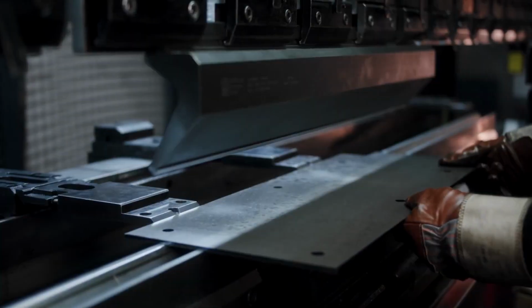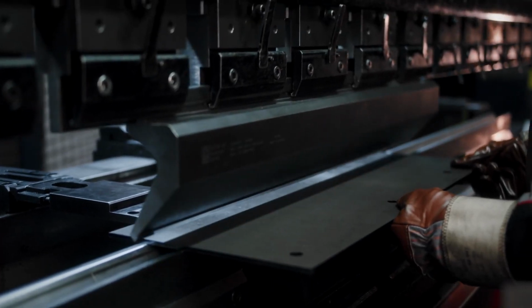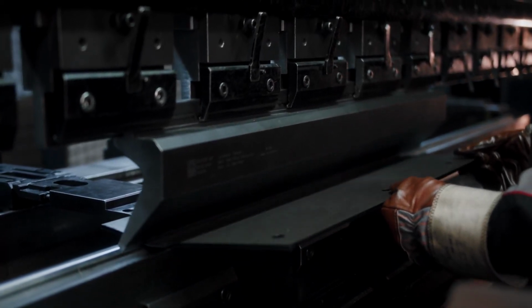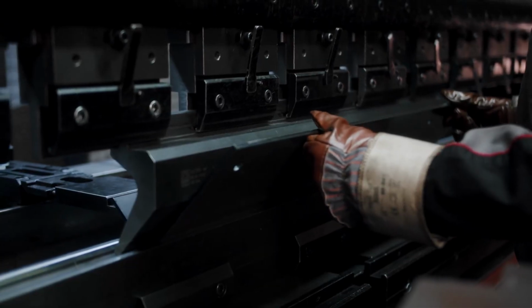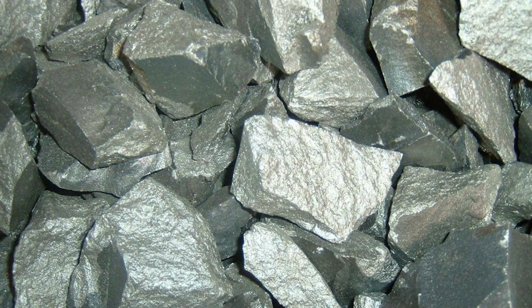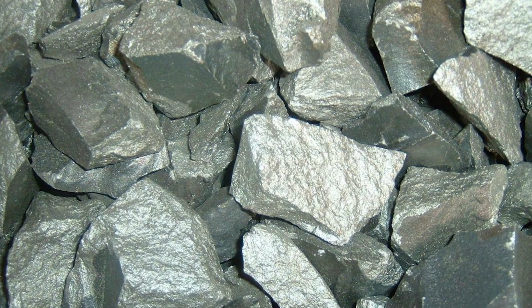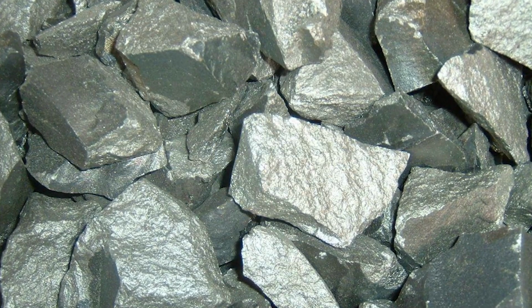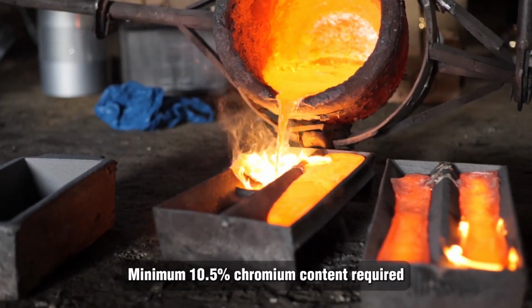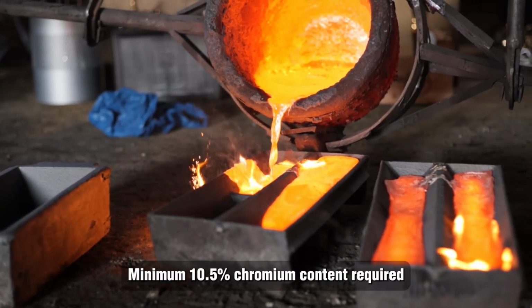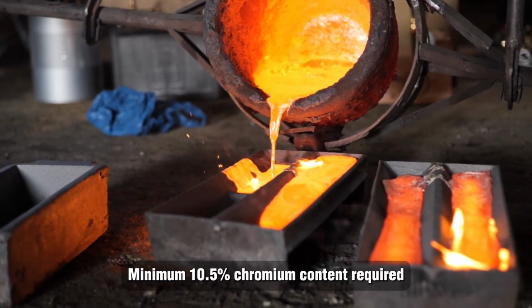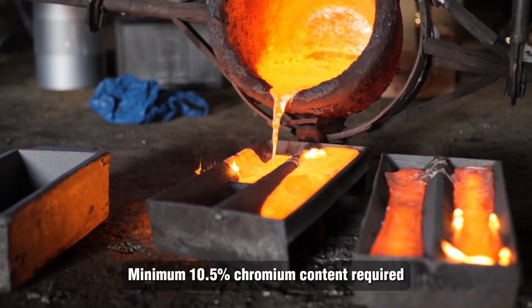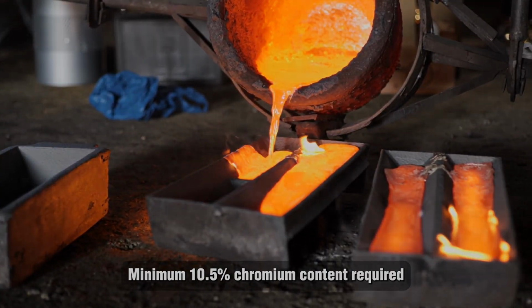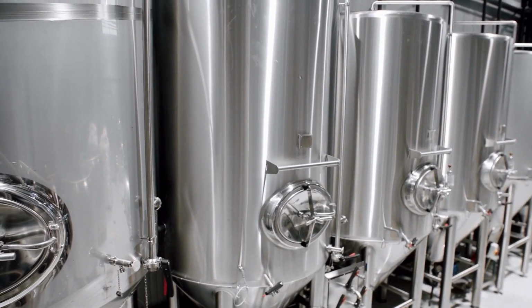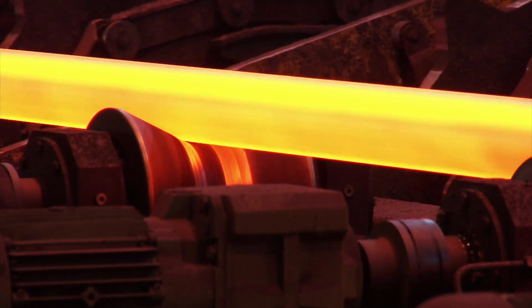Here's the science behind the shine. Chromium reacts with oxygen to form an incredibly thin, essentially invisible layer of chromium oxide across the surface of the steel. That microscopic barrier is the entire secret. It's what stops oxidation in its tracks and protects the metal underneath from ever breaking down. To get chromium into the mix, it's introduced as ferrochrome, an iron-chromium alloy, added directly into the molten iron.